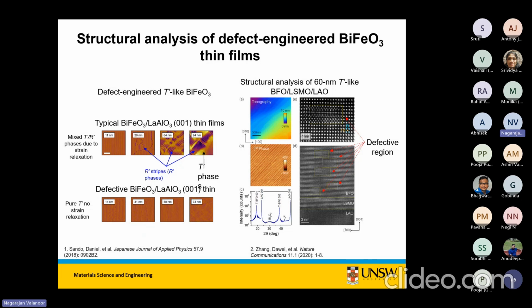For our chamber, because of the growth rate, which is being so slow, it's losing bismuth. So what happens is that you start getting these stacking faults, where the loss of bismuth means that the iron oxide stacks on itself, and then the bismuth oxide stacks on itself. Okay, so you have a self-correcting mechanism where you start to get this entire array of stacking faults, and the stacking faults are also imposing that lattice strain.